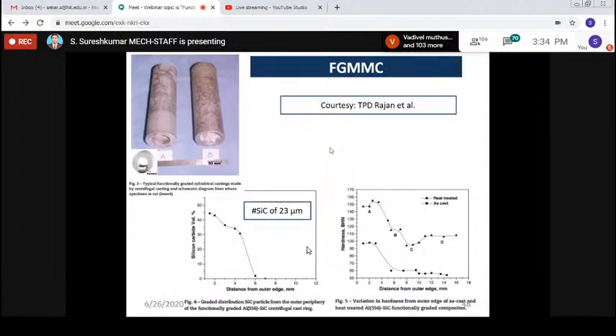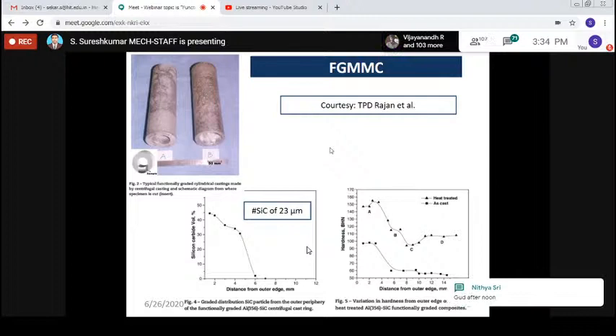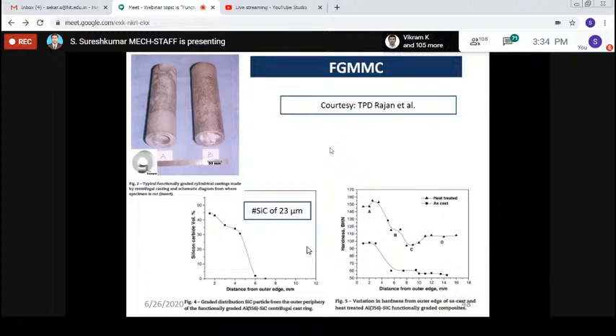In a paper by TPD Rajan and others, he produced a functionally graded hollow cylinder and made observations. The volume of silicon carbide, the reinforcement present throughout the section, maybe at the outer periphery, and what is the amount at the inner section. The left side graph shows that at the outer section, the reinforcement percentage may be 45. When you are moving towards the inner region, 6 mm from the outer region, it becomes almost 4 or 5 percent. Again, at a particular point, it becomes 0. So silicon carbide is rich in the outer periphery, and it becomes lower, almost 0, in the inner section. So actually there should be variations, right?